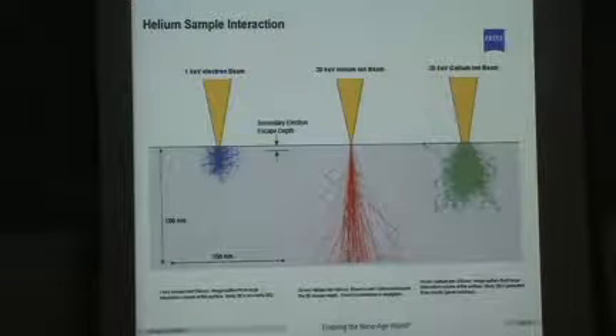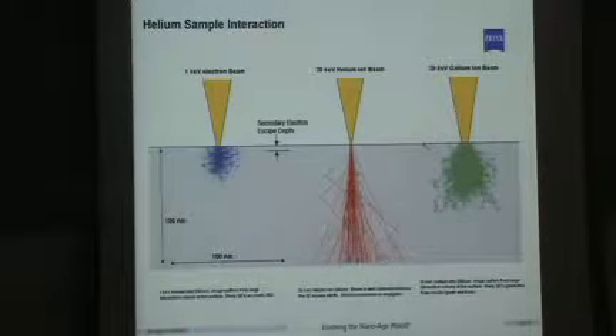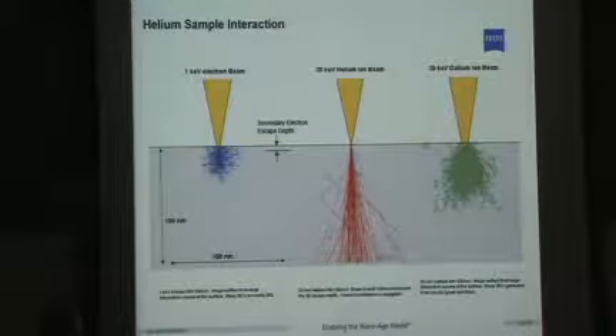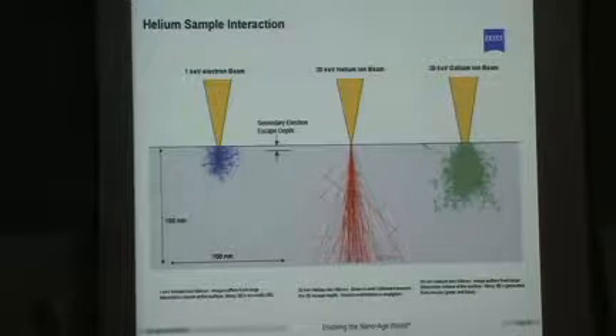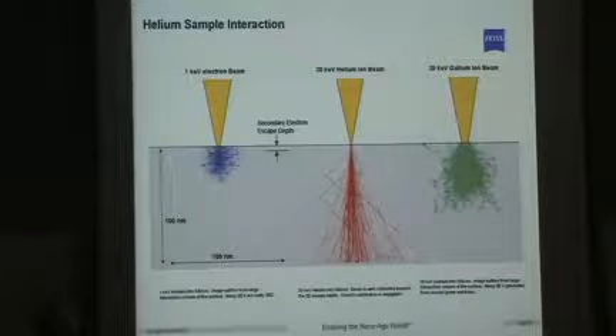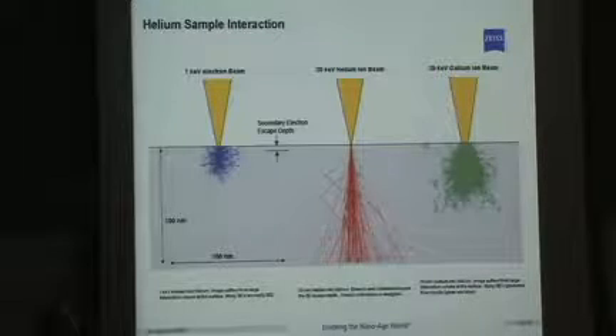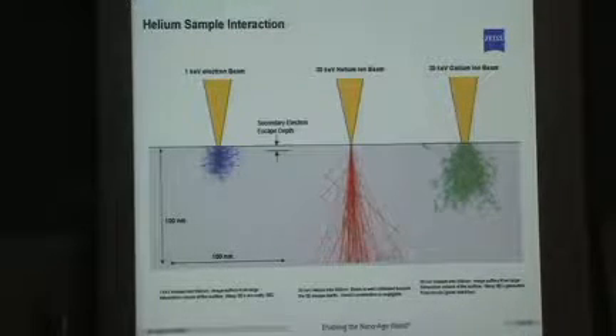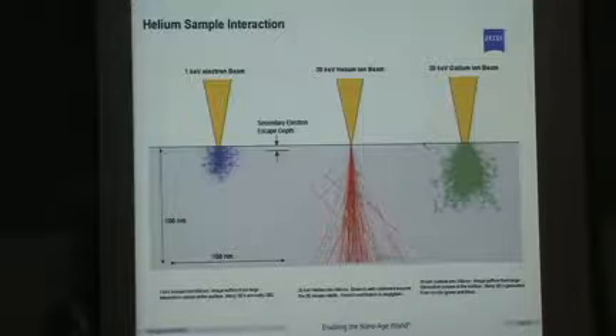But first I want to talk about that escape depth, or the depth at which the helium ions penetrate. I've got, in order of mass, the electron beam being focused down, and as the electron beam enters a sample, it's an electron, and it's mostly interacting with other electrons. So they're the same mass. So like billiard balls, they tend to have wild scattering. It hits another object of the same mass and it can go off at any angle. So underneath the surface you see this large plume. A single scattering can make it come back. That's why there's such a large backscatter contribution to electron microscope images. A lot of backscatters, you'll notice some of those backscatters can exit way over here and they can produce secondary electrons. That limits the ultimate resolution you can get unless you do special filtering processes with an electron microscope image.